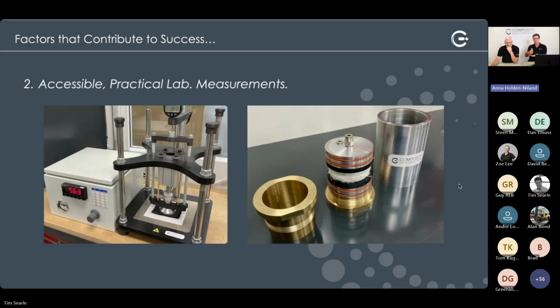And of course, those laminates that are a little bit more permeable and easier to infuse. So this is a little bit new for us. We're preparing to publish the data on this, but the results we get from this are incredibly promising. That whole assembly goes inside that aluminium barrel, and then we can put a surrogate or an actual resin through that to look at the permeability performance of the plies under examination. And we can go single plies or laminates up to 50. So it's real world stuff, and we can generate this data really quickly.